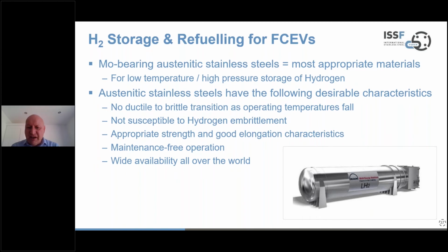Here we have a hydrogen storage system shown in the photograph at the bottom, but molybdenum bearing stainless steels are the most appropriate material for this low temperature, high pressure application. That's because these types of stainless steels don't suffer from a ductile to brittle transition as the operating temperature falls. They are not susceptible to hydrogen embrittlement, obviously when storing hydrogen. They retain their strength and good elongation characteristics. They will provide pretty much maintenance-free operation, and it's a widely available product, one of the very common stainless products available all over the world.